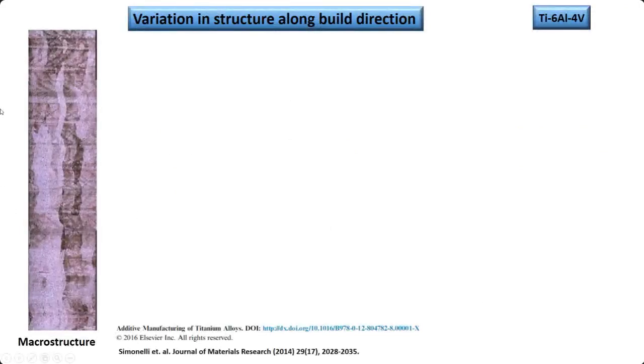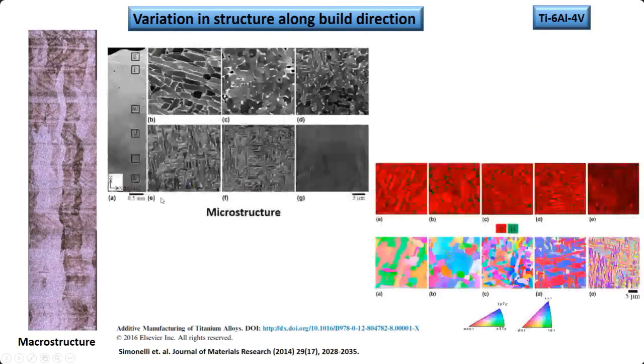When we look into the additively manufactured structure, this is how the macrostructure looks. You can see these bands very clearly, and this signifies the grains - the prior beta grains can be seen here, quite big. If we investigate the microstructure at different levels, at different layers starting from B to G, there are distinct changes in the microstructure. This is very much fascinating.